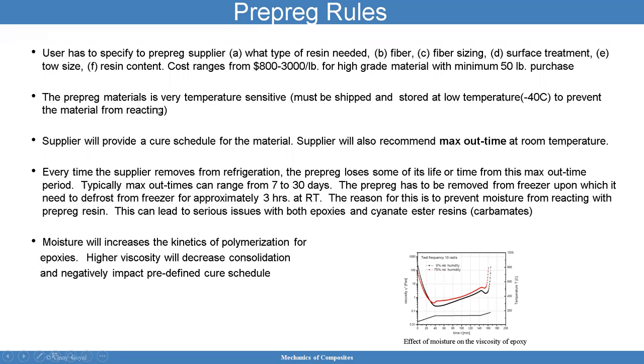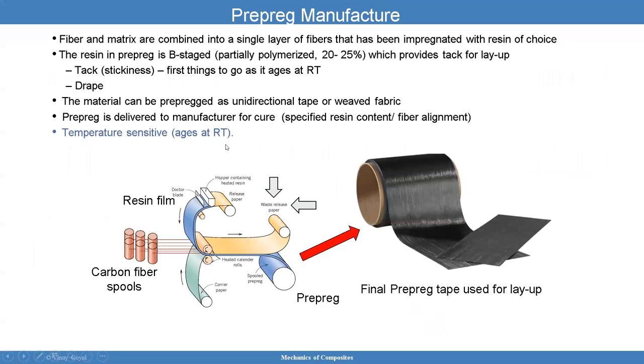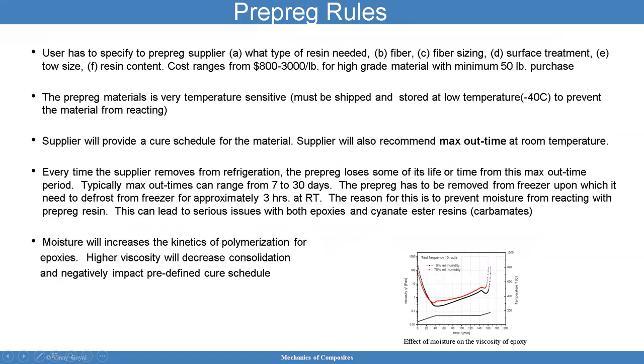The prepreg materials are very temperature sensitive, and it must be shipped and stored at low temperatures. We discussed that earlier, at minus 40 C typically, to prevent the material from reacting. The supplier will provide a cure schedule for the material, and then the supplier will also provide a recommended max out time at room temperature. What I mean with that is, this roll of composite lamina is a prepreg, and that's going to be stored at minus 40 C and shipped to you. Now, you have to do some work on it. You have to cut it, you have to put things together. To be able to do that, the manufacturer typically will say, okay, this material, if it's left outside, can stay out for so long. And so that's what I mean with out time.